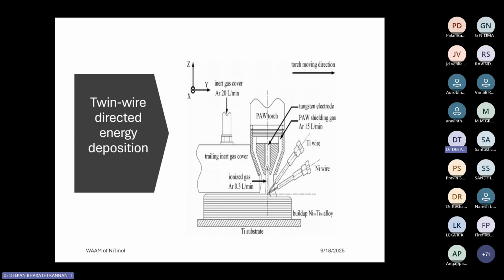Another advancement that some people have explored with respect to nitinol is twin wire directed energy deposition. This was done with a plasma arc torch, and you could see it on the right side. There are two wires, one titanium, another nickel. So according to our requirement, we can control the feed rate of the titanium wire and nickel wire so that we can control the composition also. Composition plays an important role with respect to all the properties of nitinol shape memory alloy.